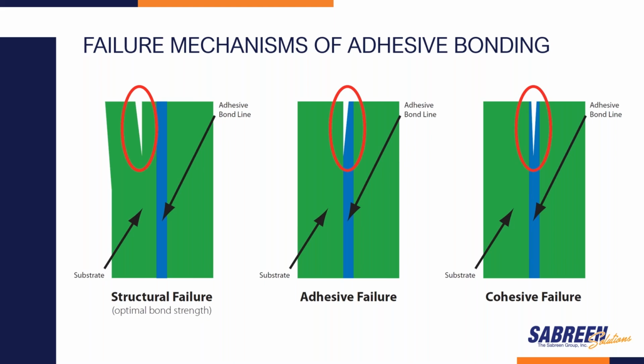Obviously, we want to achieve a stronger bond, and that would be the cohesive failure on the right. And in this failure mechanism, the adhesive splits within itself, meaning that we have achieved the full strength of the adhesive that we're trying to bond. On the far left is structural failure. It's always great if we could achieve this.